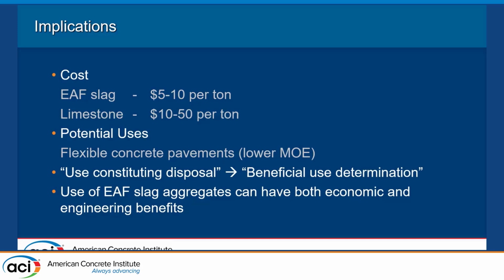And as for potential uses, we believe the main application of electric arc furnace slag aggregates could be in more flexible concrete pavements due to the previously mentioned lower modulus of elasticity, which could allow for concrete pavements to be used more in areas where freeze-thaw damage is more of an issue, which the added flexibility will help with. And as well, using this material as a coarse aggregate will introduce a use for it that is meaningful and has positive impacts and is not just being disposed of and creating environmental issues. And overall, these slag aggregates can have both economic and engineering benefits to our concrete industry.